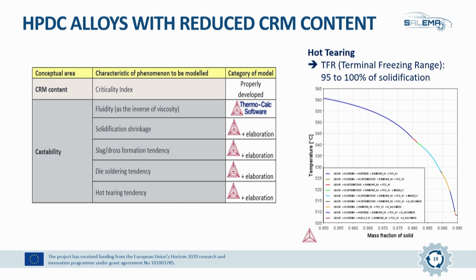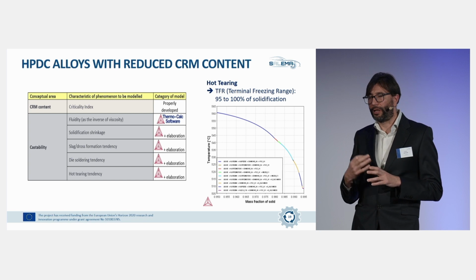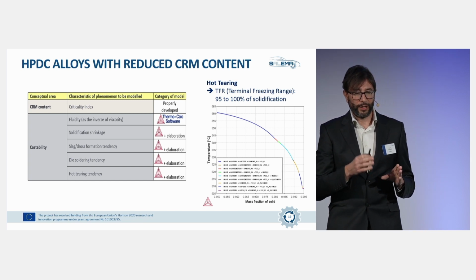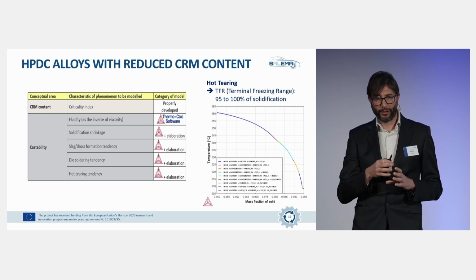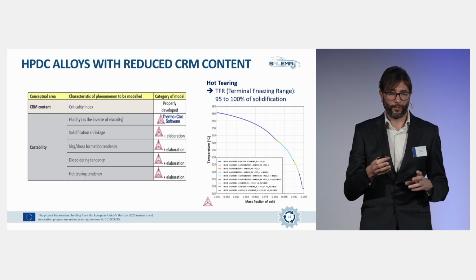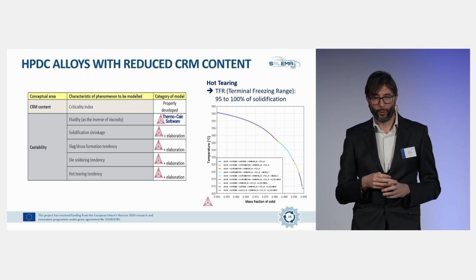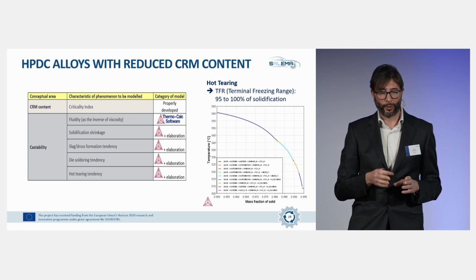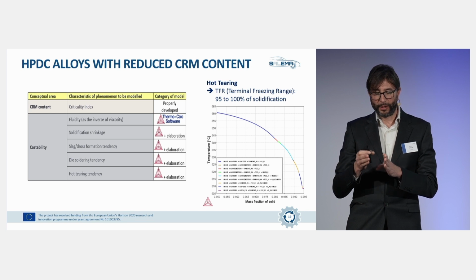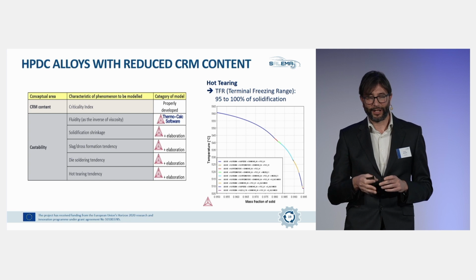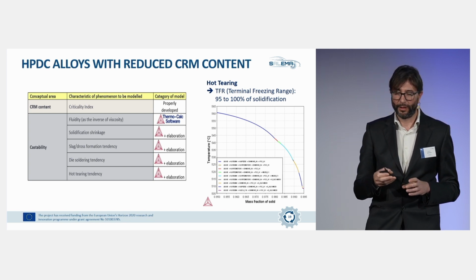additionally to these high scrap content alloys, we work on new alloying systems with lower silicon and magnesium content. For that, we use what we previously defined in another project, a CRM content, a criticality index, we call it, that gives us a value of how critical the alloy is, and it depends on the elements that the alloy has. And then, at the University of Padua, they predict by using Thermo-Calc, thermodynamic simulation software, and in some cases their own elaboration, as can be seen here, for example, for hot tearing, where they determine the temperature gap for the terminal freezing range, that is the solidification from 95 to 100%.